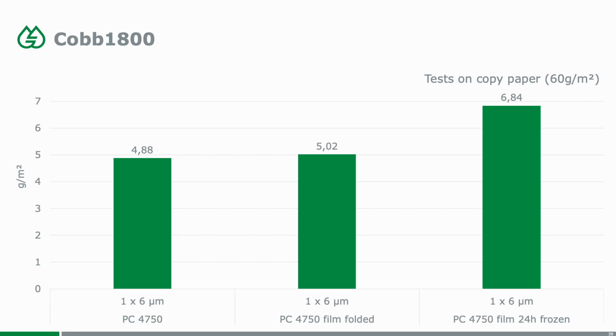Here we look at COBB 1800 values, so half an hour water resistance on the copy paper. So on the left hand side we see the PC 4750 without mechanical stress around 5. Then if you fold the film, nothing really changes, so it remains as it was before, which indicates that the flexibility of the product is sufficient. And then if you freeze the film for 24 hours at -20 degrees, it goes slightly up to 6.8, but that's still, let's say, a marginal difference and no real harm done to the barrier layer.